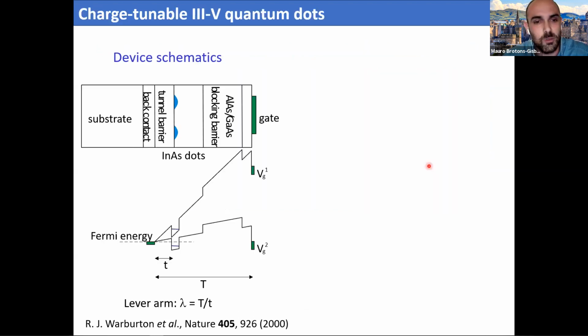So now we can go to what I was mentioning. The way people traditionally control the charge state in a III-V quantum dot is the following. We have our quantum dots. Basically, you have our confined states, and these confined states are separated by a tunnel barrier from a, let's say, reservoir of electrons, in this case a Fermi reservoir, that's basically in the back contact. And by applying a gate voltage between the back contact and the top gate, we can tune the energy difference between our confined states and our Fermi level, okay?